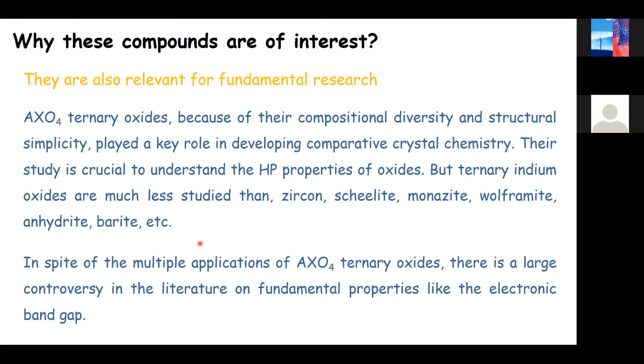In spite of that, there is an important thing related to basic research, which is the fact that there is a big controversy in the literature regarding the fundamental properties of these materials, in particular regarding the band gap. As I will show later, you can find for a given compound, for instance, indium vanadate, different reports of the band gap energy, which can go from nearly 2 to 4 point something eV, which is a huge difference. And that's not possible. So we need to do some accurate determination of the band gap energy, which will be crucial to know if this material can be applied or not in different technological applications.